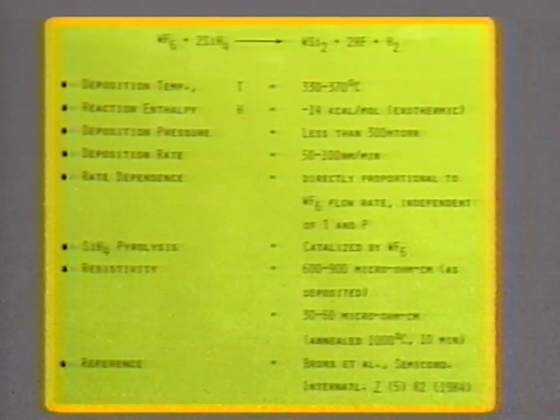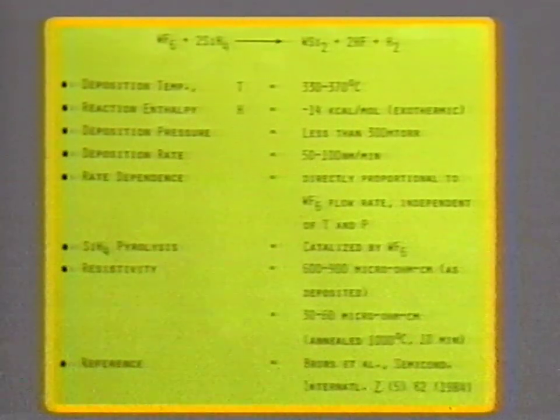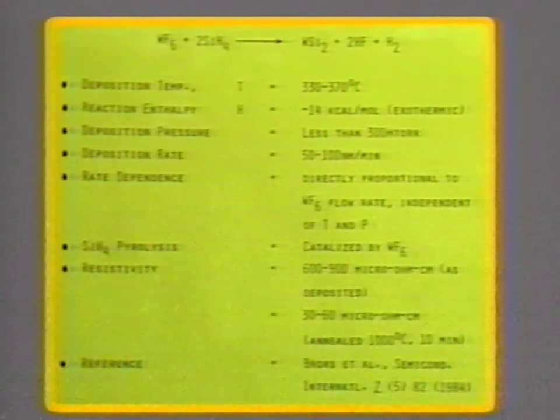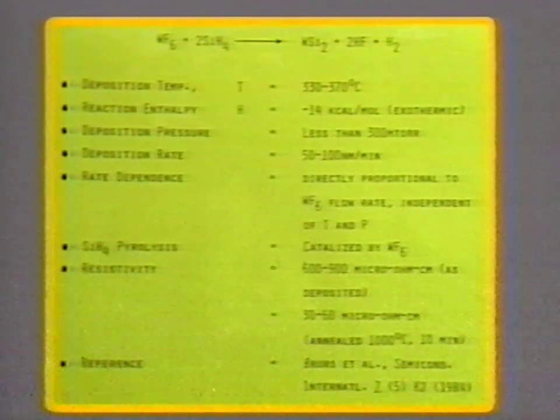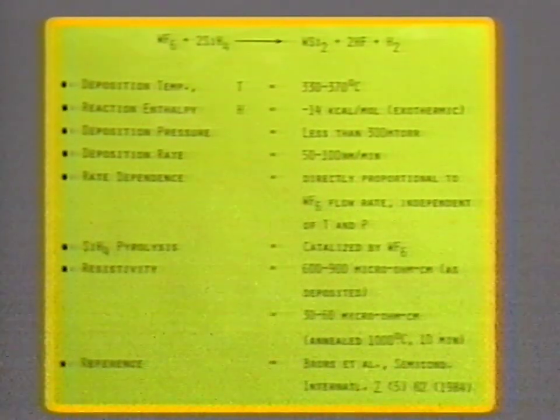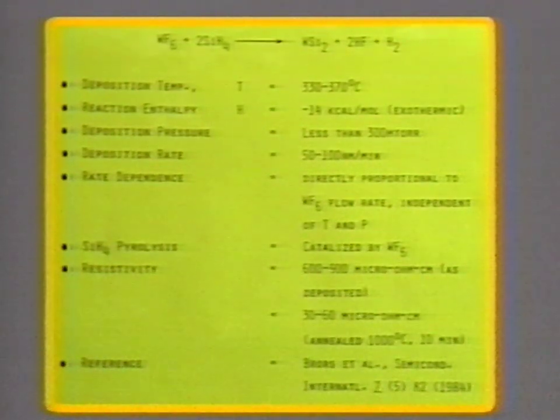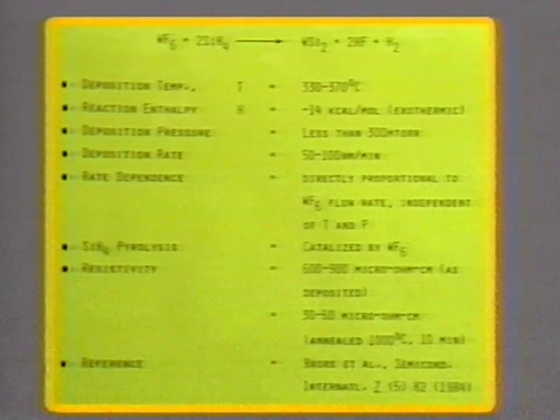The interesting thing here perhaps to point out is that the rate dependence is directly proportional to the tungsten hexafluoride flow rate and is independent of temperature and pressure. There is one other strange aspect here, namely the effect of tungsten hexafluoride on the silane molecule itself. There is a good degree of evidence that there is a catalysis taking place, namely the tungsten hexafluoride catalyzing the pyrolysis of the silane to silicon, because otherwise we would not be able to run the reaction as shown here. So this actually helps in this case.